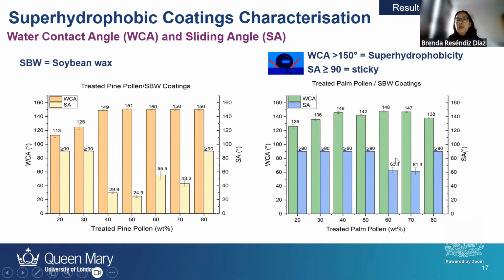So when I use palm pollen, I can also observe that the water contact angle was lower. I couldn't even achieve superhydrophobicity. Most of them were very sticky samples. So I can see that maybe this system between palm pollen and soybean wax was not the best.